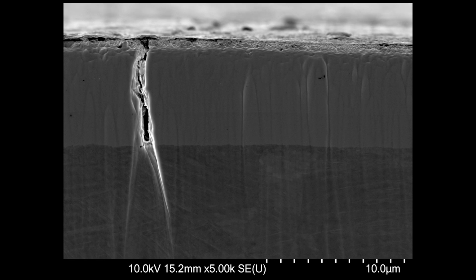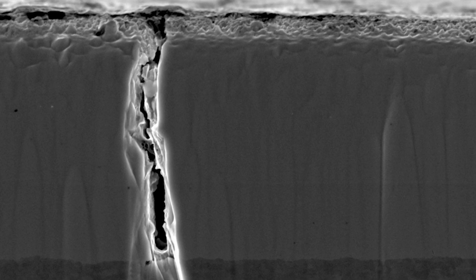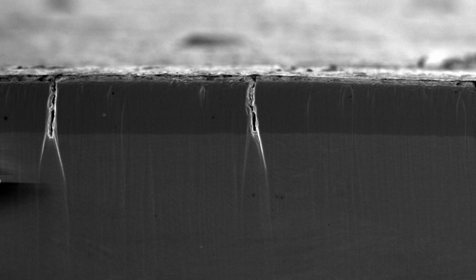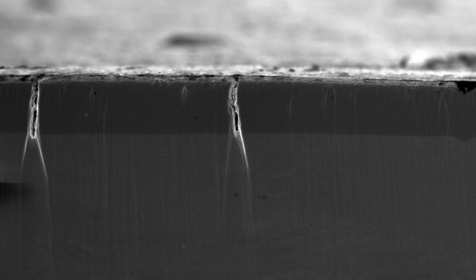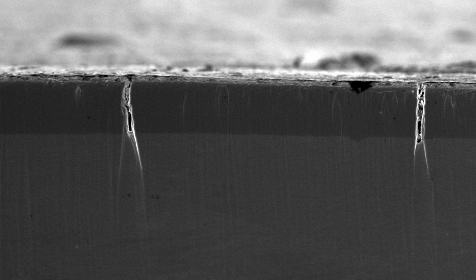I have no clue. The only other thing I can really say about this case is that there are a lot, and I mean a lot, of these cracks in the nickel coating. You can see pretty clearly they are going all the way from the surface down to the brass. So, given some extreme environmental circumstances, could this nickel coating fail to completely protect the brass underneath? Maybe. Will it cause any problems with the functionality of the gun? No. But with that said, I mean, these cracks probably shouldn't be there.